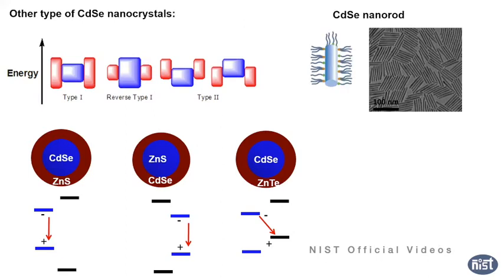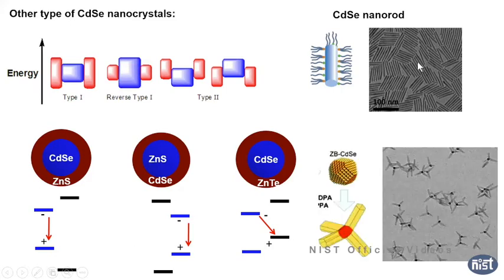And as I told you, we can grow very nice nanorods. You can see these are very nice nanorods, grown by adding different ligands, and the lengths of all the rods are very uniform. Also the tetrapod, from the simple crystal you can grow the tetrapod. You can see only 3 legs, but the other leg is behind the dots, so you cannot see all 4 legs because it's only a 2-dimensional view, not a 3D view. In a 3D view you can see the 4 legs, but you nicely grow from one side of the crystals.